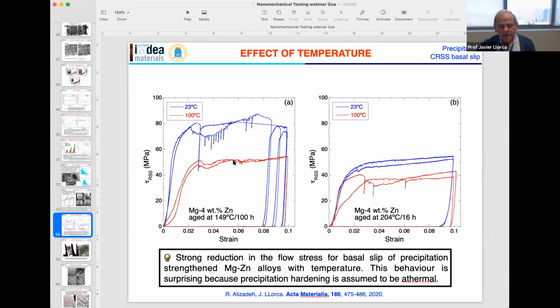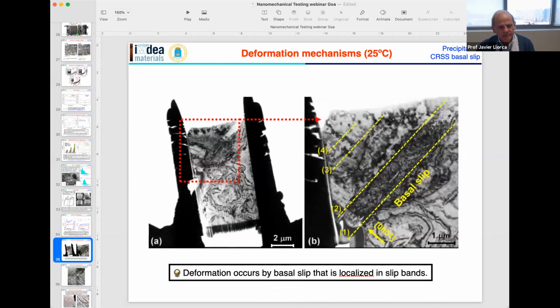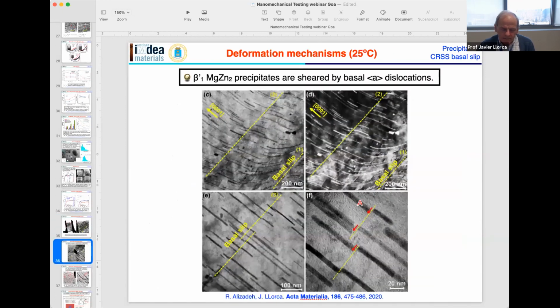This is surprising because normally precipitate strengthening is known to be an athermal mechanism. But of course, something is going on here that makes this a thermally activated mechanism in this particular case. We looked at the deformation mechanism. We took one micropillar, made a thin lamella parallel to the micropillar, and looked at it in the TEM. In this region, you have slip bands where the deformation has been localized. And when you go to higher magnification, you see these very nice pictures.